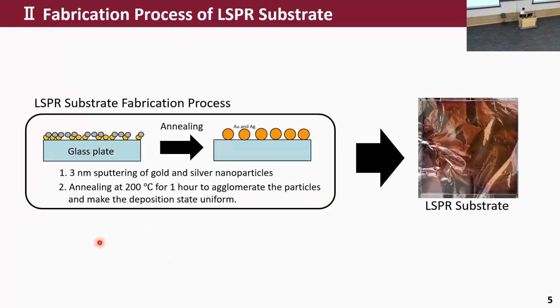Fabrication process of LSPR substrate. The LSPR substrates used in the experiment were prepared by sputtering gold nanoparticles and silver nanoparticles onto a glass. Next, annealing at 200 Celsius for 1 hour to agglomerate the particles on the substrate surface and make the deposition state uniform.